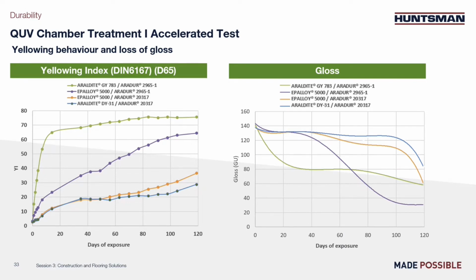We cannot guarantee that it will never yellow, but it resists about 100 days in the QUV chamber, and we then see the loss of gloss, also the degradation of the surface. It is the blue curve. So Araldite DY31 seems to give slightly better results than Epalloy 5000, which is the orange curve, and it's due to the higher hardness of the system when you use Araldite DY31 versus Epalloy 5000.